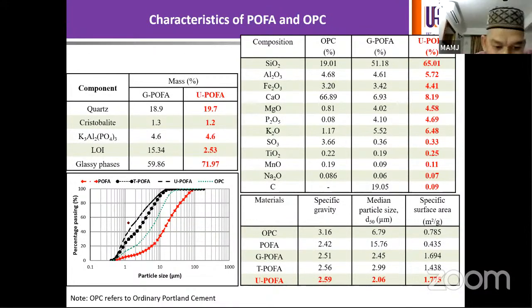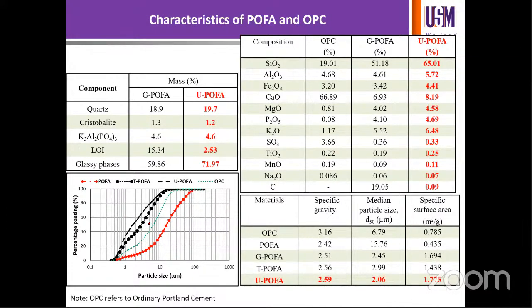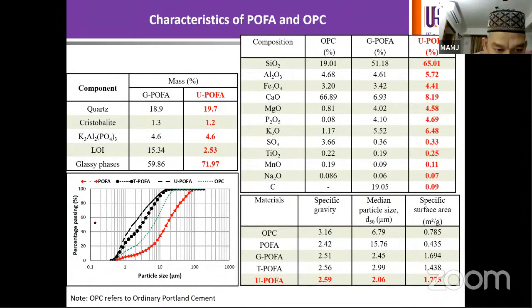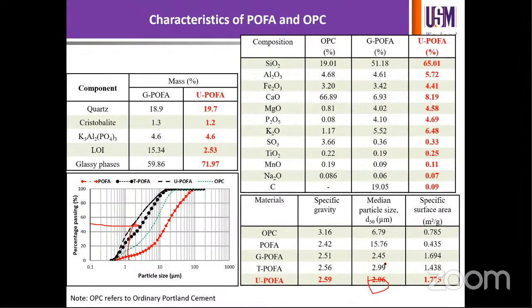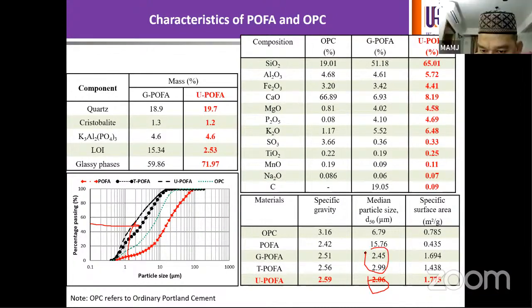And down here, in terms of particle size analysis, we can see the difference between OPC, T-POFA, as well as U-POFA. There is a significant difference in terms of particle size, whereby the U-POFA is about 2.06 in median particle size, as shown down here, in comparison to the T-POFA and G-POFA. So the processes that have been undertaken to refine the material, we can claim, work to enhance the characteristics and the pozzolanic properties of the material.